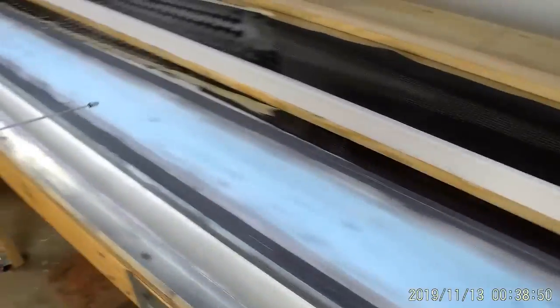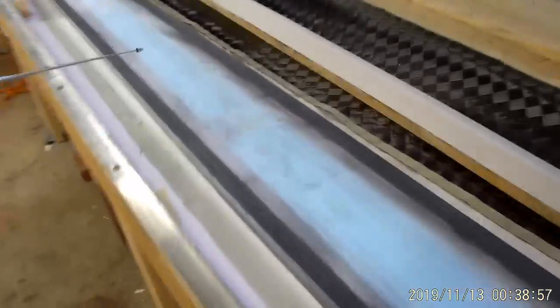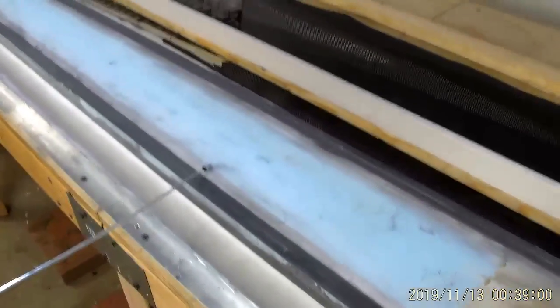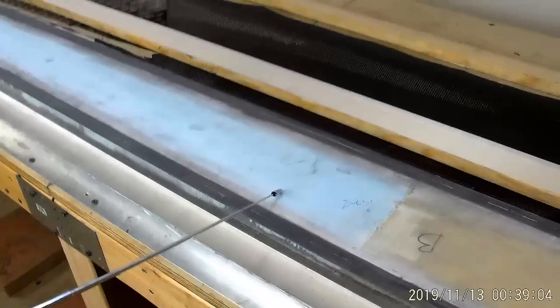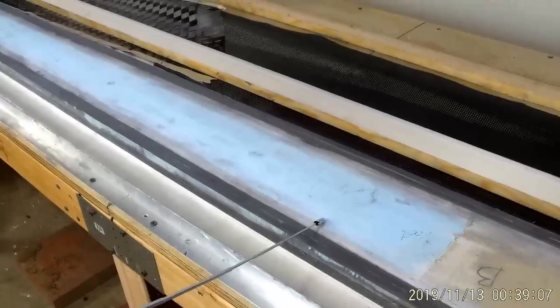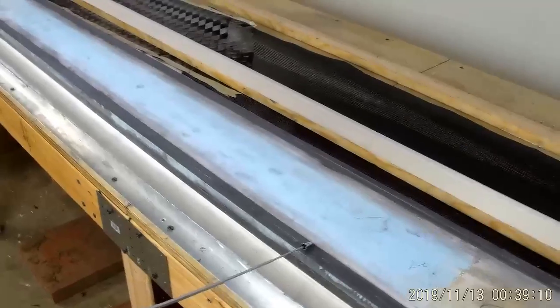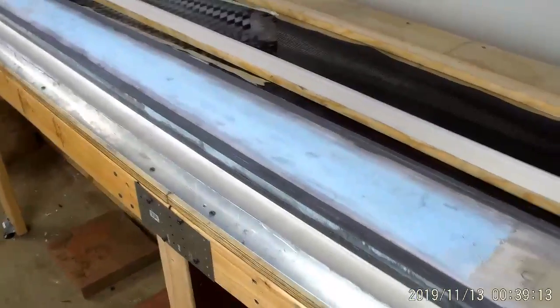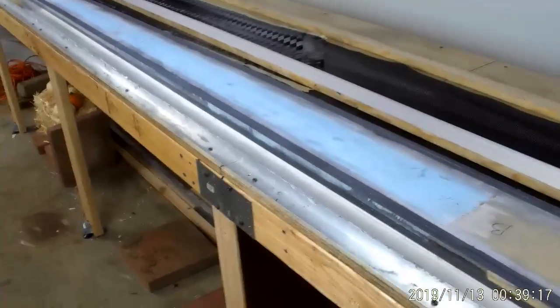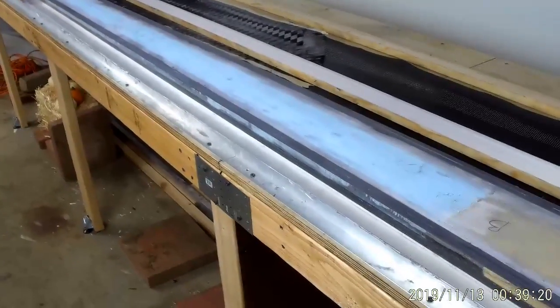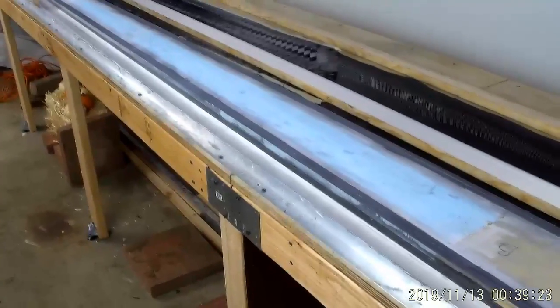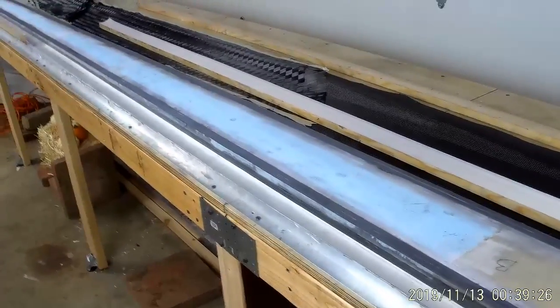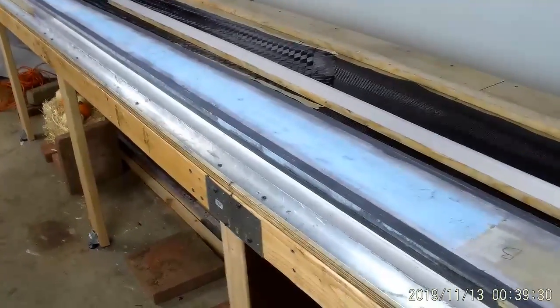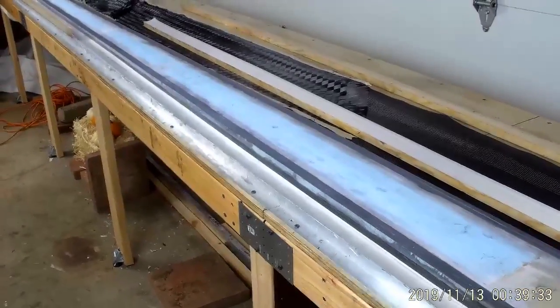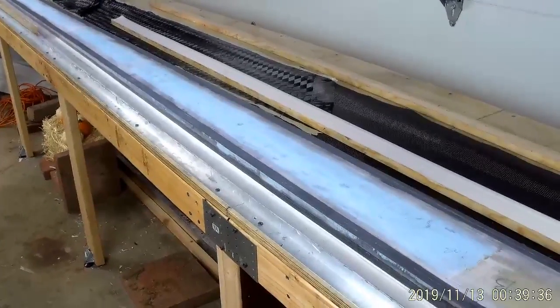I'll give you the kind of difference it makes. You may remember on the front side of this, there's a stretch here, from about here to here, actually runs further out, of the PVC foam, which has a much more open cell structure on it. And on one of the spars, I left that open. On the other spar, I filled it in with microballoon filler, the lightweight microballoon filler that's used for models. And the difference was about 2 ounces in the weight of the spar. So out of a little under 9-pound spar, 2 ounces was just in resin going into filling up those cells that provides no strength whatsoever. Coming in with microballoons, lightweight filler, saves those 2 ounces, a little bit more work, makes all the difference.